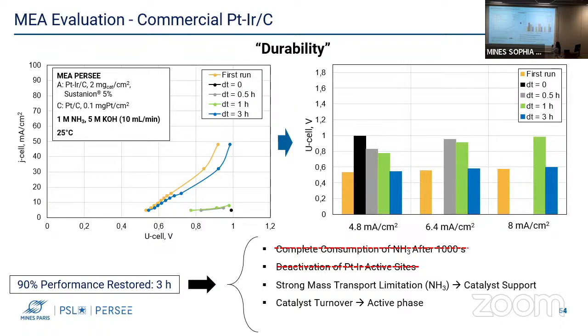This leaves us with 2 possible explanations, which are the mass transport limitations for ammonia inside the catalyst support, which means that we should find a support having an optimum pore size, or it's a matter of catalyst turnover, which means that we should research more active catalysts.